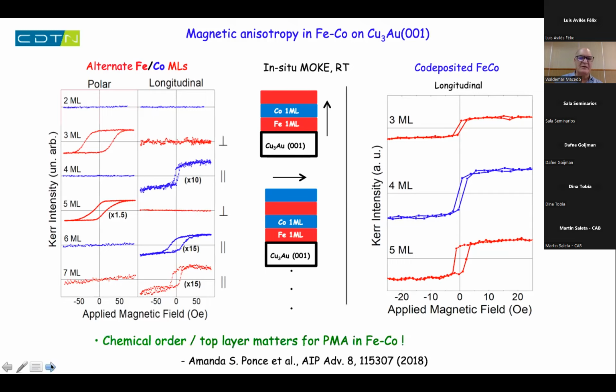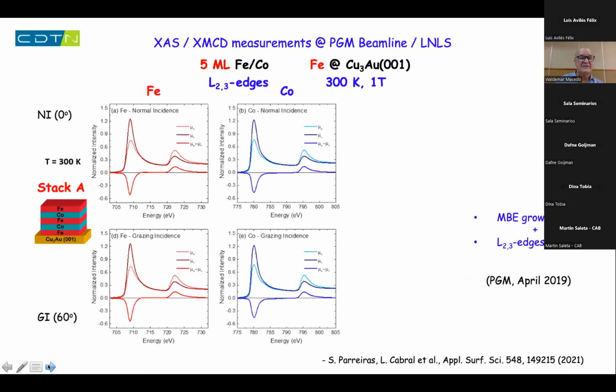That means we really have shown that the chemical order matters for the anisotropy of iron for ordered iron cobalt on top of the Cu3Au. That means, but we are not able to do 1 monolayer iron-57 resolved Mössbauer spectroscopy in this system because we are not sensitive to just 1 monolayer. For that, we would need synchrotron radiation, okay? Mössbauer with much more intensity for that. But we tried to do the same experiments in the synchrotron.